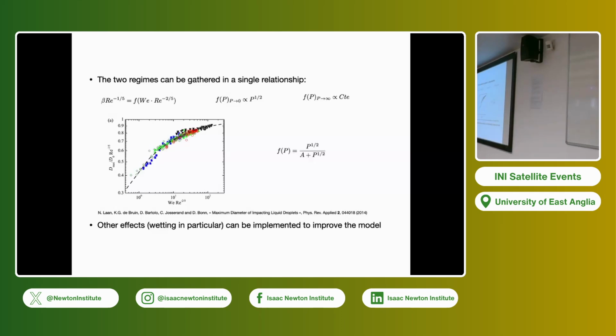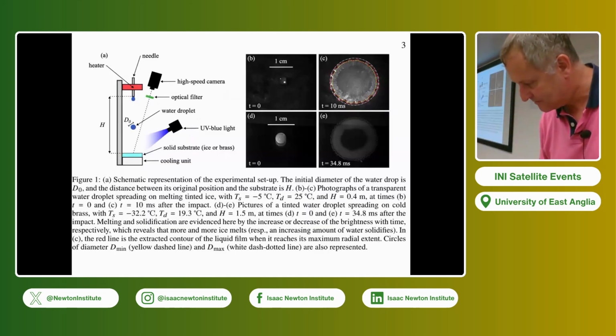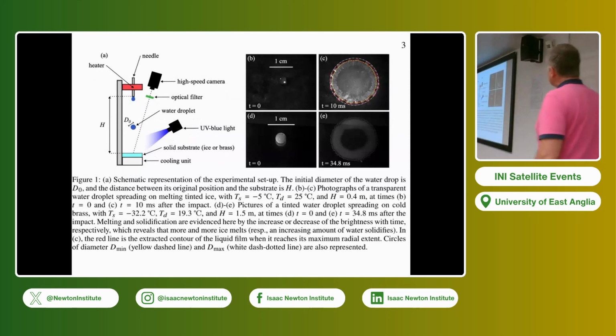What was nice, in a paper with Nicolas Laan and the group of Daniel Bonn, is that we could collapse all the experimental data of the literature on a single curve, and this curve was easily fitted using a Padé approximant. So the question now is what happens if you consider solidification and melting? We have this theory of spreading. So we did two types of experiments. The first one, actually the last one that I will present first, is a drop impacting on the ice layer.